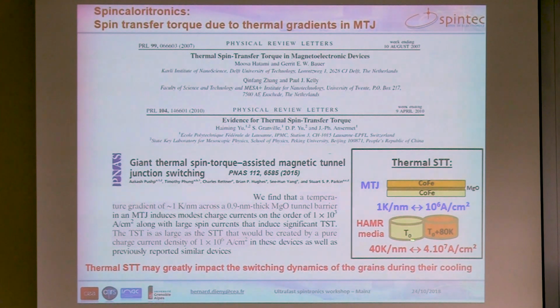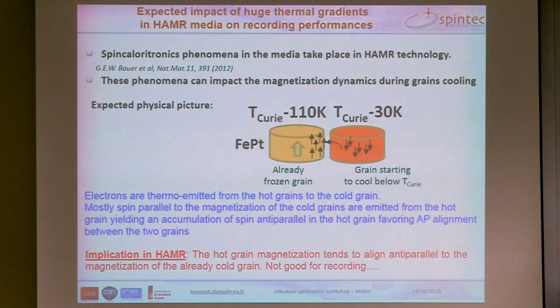Now, we can consider that 2 grains separated by a grain boundary is similar to a magnetic tunnel junction. We have 2 magnetic electrodes with a tunnel barrier in between. So we have the same physics as in a magnetic tunnel junction, with a very large thermal gradient. The physical principle is identical, but the geometry is different. So the conclusion is that we can expect quite significant spin caloritronics effect and thermal spin transfer torque taking place in the media in HAMR recording, and that this effect can impact the recording process during the cooling of the grains.